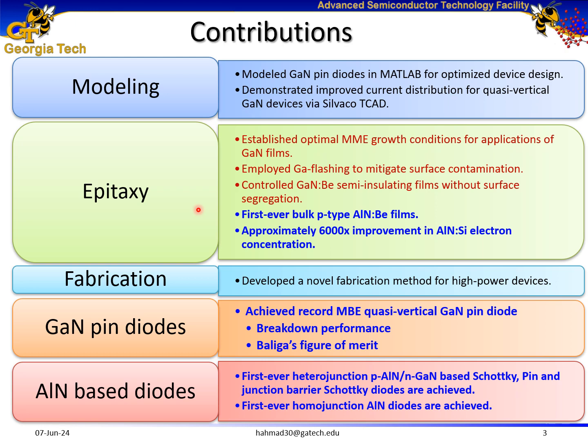I have shown controlled beryllium-doped gallium nitride semi-insulating films without surface segregation. I have achieved the first ever bulk P-type beryllium-doped aluminum nitride films. I have achieved approximately 6,000 times improvement in silicon-doped aluminum nitride electron concentration.